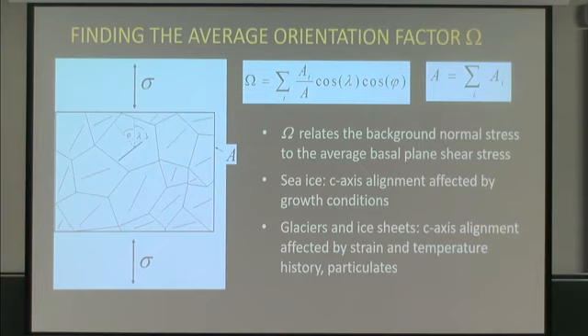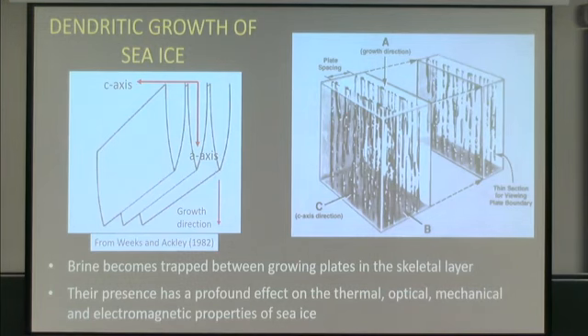It's a real key issue in glaciers and ice sheet motion because this fabric is constantly evolving. Sea ice tends to grow with the fabric and doesn't recrystallize in the way that ice does in glaciers and ice sheets. So in general, the structure and the orientation, the fabric that develops upon growth, is the one you would use to characterize it for your calculations with this approach. So just to give you a quick idea of how this structure gets there, freshwater ice grows with a planar interface, and it tends to do a very good job of eliminating contaminants and any kind of second phase in the solution. Sea ice, when you add enough salt to the water, starts up this dendritic growth process.